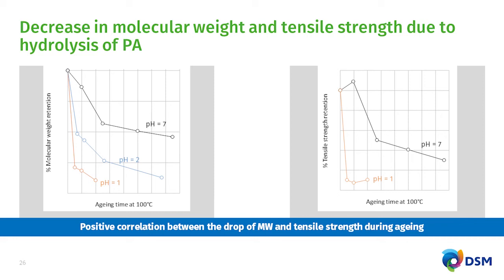In this case, it is polyamide 4,6. This reduction in molecular weight also has a direct link to the tensile strength retention, as you can see in the right-hand side figure. In essence, if you have a polymer with better chemical resistance, the molecular weight is more or less intact, and as a result, the tensile strength is also more or less intact.